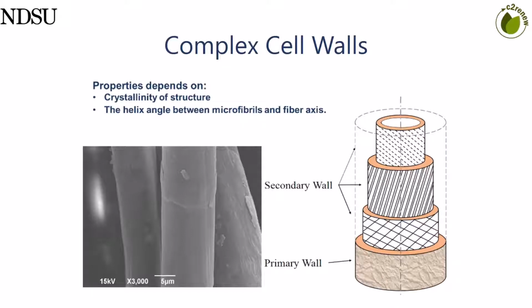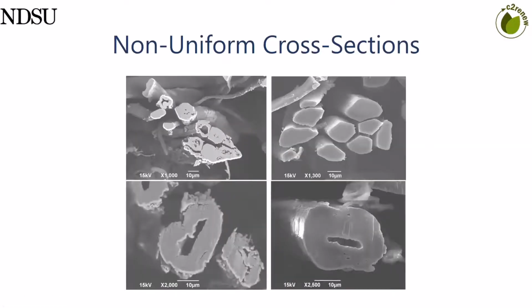And what we found, and others have studied as well, is that the angle at which the cellulose grows during the growth period really determines that strength. If you've got a greater angle off axis to the fiber, you have a much lower modulus or lower stiffness fiber, as opposed to having the cellulose constituents growing along the axis of the fiber as it's being grown.